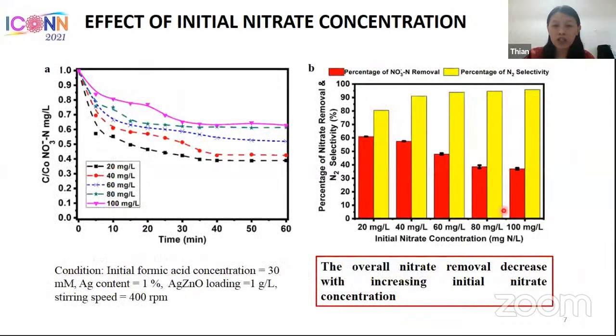And then the next parameter is the initial nitrate concentration. So again, in this figure B here, we can see if we keep on increasing the initial nitrate concentration from 20 milligram to 100 milligram per liter, there is a gradual decrease in the percentage of removal. And this can be rationalized on the basis that if we keep on increasing the amount of nitrate molecules in the solution, they will adsorb more and more to the surface of the photocatalyst, but at the same time, the amount of photons reaching the surface of our photocatalyst remains the same. So hence, increasing the concentration of nitrate is not helping, it's not increasing our percentage of removal.